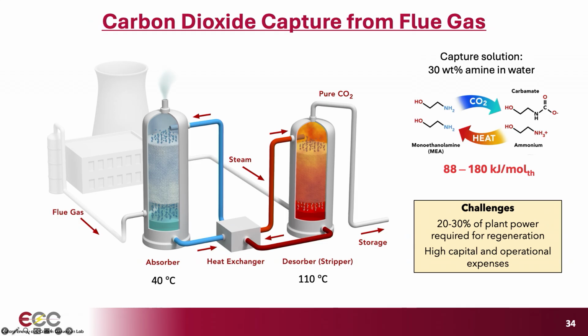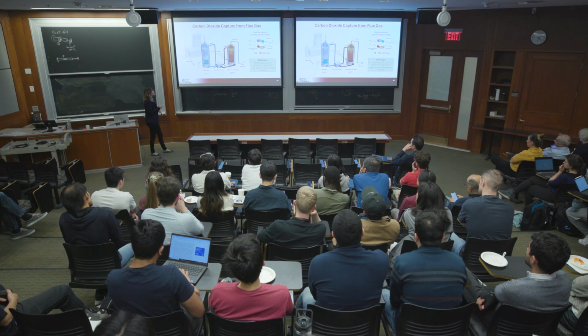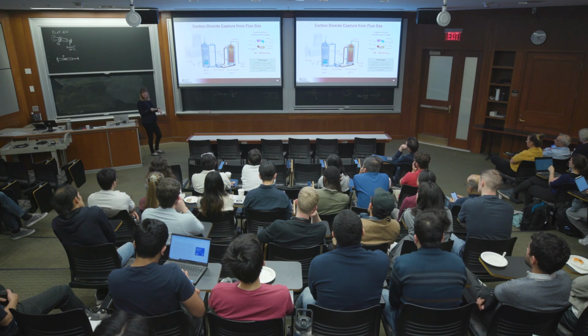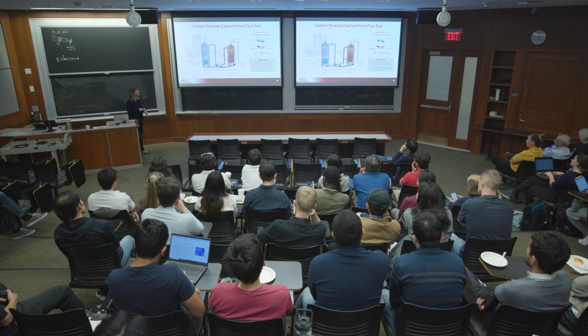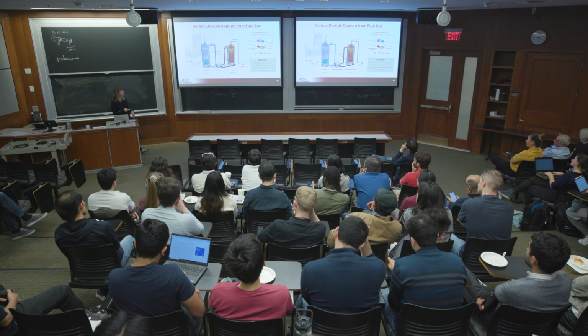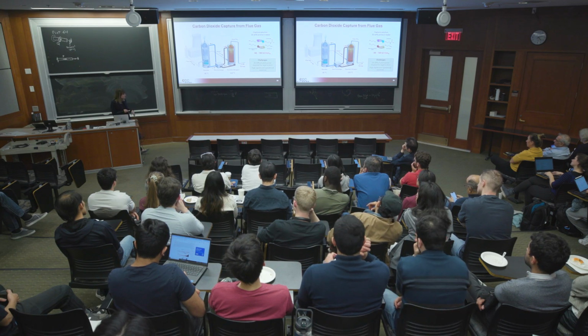So in conventional CO2 capture, we use a sorbent, typically an amine such as monoethanolamine shown here. And we bubble the flue gas through the sorbent, typically at temperatures around 40 degrees C. Then a reaction happens. Two amine molecules in this case react to bind one CO2, and we form a carbamate species and an ammonium species stoichiometrically alongside. And then once this solution is saturated, we run it through a desorber at higher temperature. So we apply heat to reverse the reaction, bubble off CO2, and the output of this process is a concentrated CO2 stream that you can presumably store or do something with.